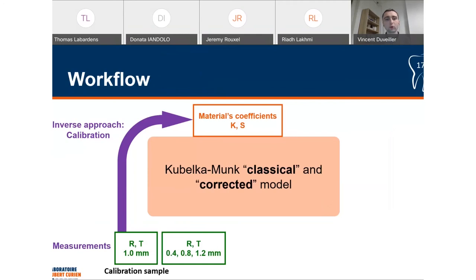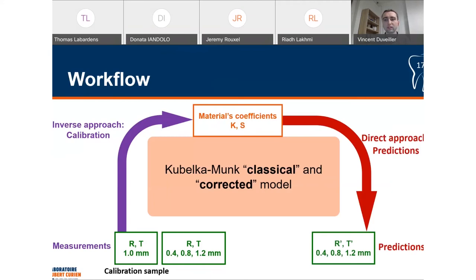So now let me show you the workflow of this experiment. We measured the reflectance and transmittance factors of our four samples. Then we need to calibrate the Kubelka-Munk model. So we took the sample with thickness 1 millimeter and used it as a calibration sample. This means that we applied the inverse approach on the reflectance and transmittance measurements of this sample to derive the material's absorption and scattering coefficients, K and S. Knowing these coefficients, we are able to predict the reflectance and transmittance factors for the different thicknesses by applying the direct approach.